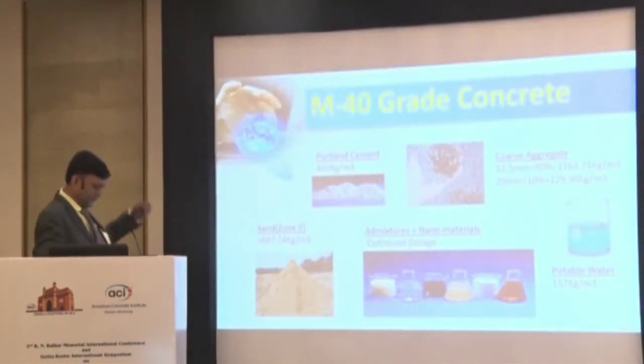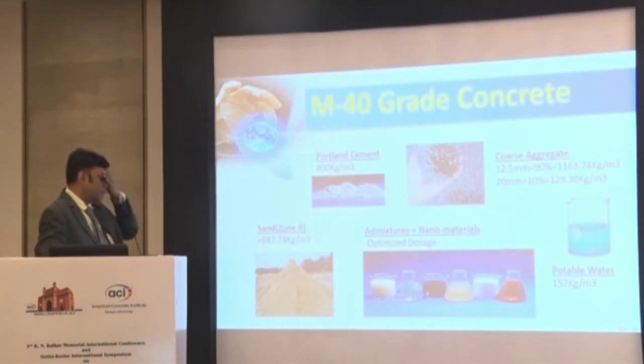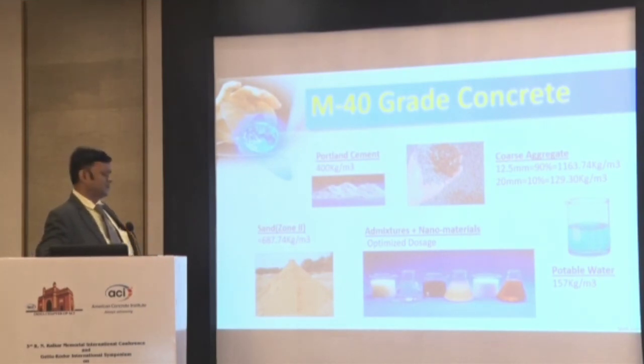Now I repeated this optimization from mortar to concrete, M40 concrete. I have used IS 10262. My water cement ratio is kept fixed at 0.4, sand zone 2, and coarse aggregate 90 and 10%, Portland cement 400 kg per meter cube, potable water as per mix design. So we will not go into details. So what quality I got at 28 days, 90 days, 180 days.